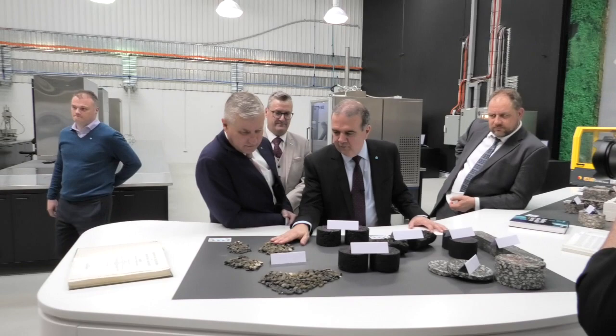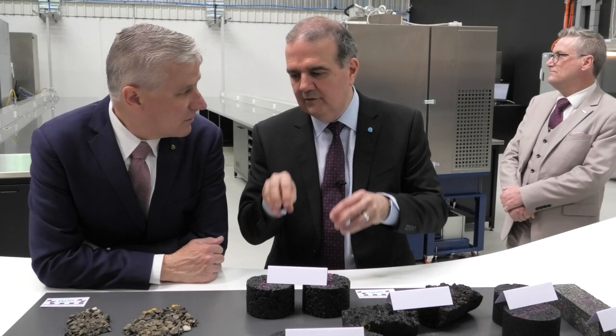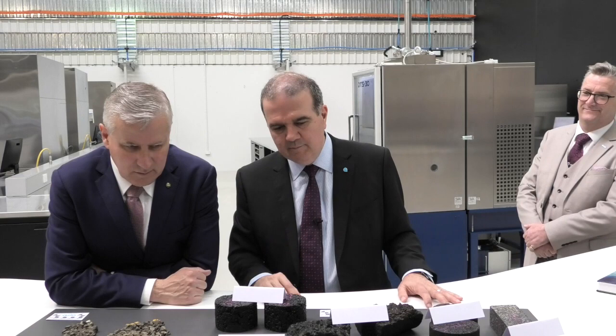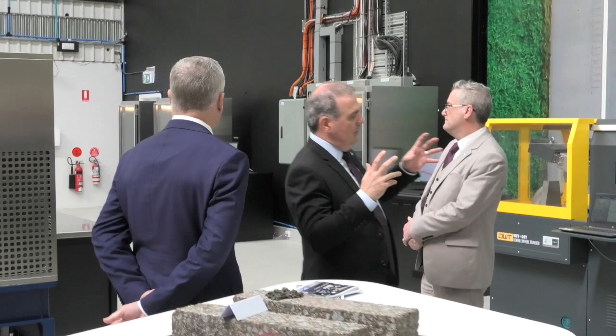This is a spray seal — typical for rural and regional roads. We're world leaders in the technology behind it, but we're losing the skill sets across the country. It's about reinvigorating those skills, understanding bitumens better — we're importing bitumens from Singapore now, having switched from Saudi Arabian crudes about a decade ago. A practical example: the Gympie Bypass project is using a high-modulus asphalt bitumen developed here at ARRB in partnership with the Department of Transport. It's going to save seven million dollars because you can build it in a thinner layer with higher strength material.